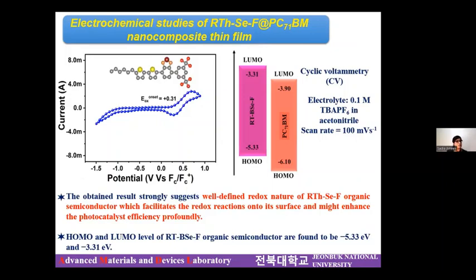And since it is an organic molecule, we performed the electrochemical characterization to obtain the HOMO and the LUMO levels. From this, we obtained the HOMO and the LUMO of the synthesized molecule. And we have found that it matches well with the HOMO and LUMO of the PCBM material. That means here we can expect efficient charge transfer, which is actually the main requirement for the photocatalytic application.